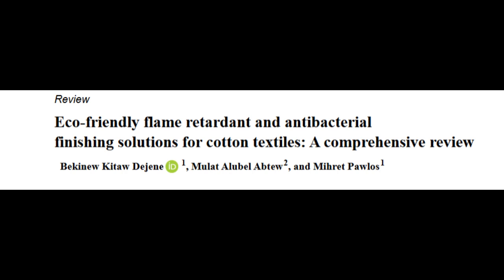Any standout examples? Well, one study showed magnesium hydroxide significantly delayed ignition time for cotton. But a common issue with these is the loading level. You often need quite a bit of the inorganic material to get good FR performance, and that can make the fabric stiff or heavy.